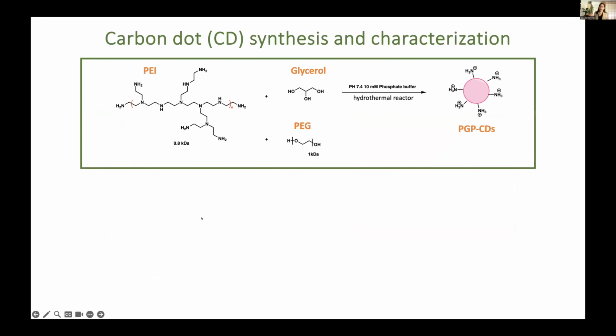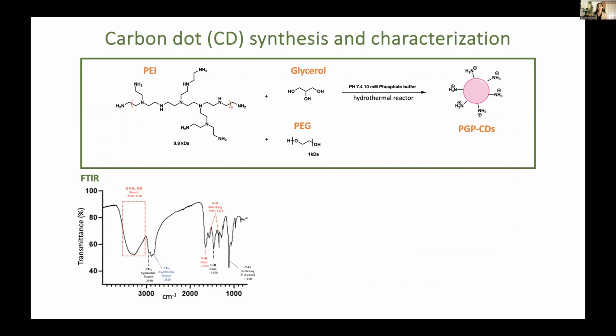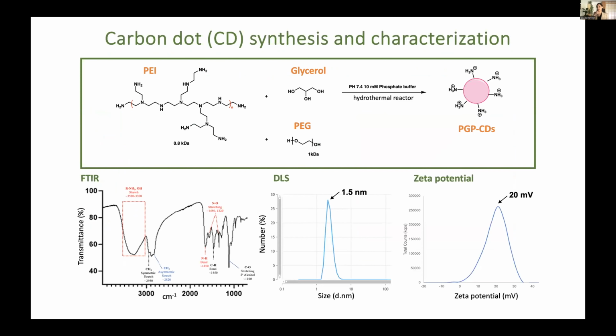So we thought that given carbon dots are very small, maybe they'll be able to enter these stem cells. So we synthesized them from a positively charged polymer, polyethylenimine, glycerol and PEG, a very easy synthesis. And then we characterized through FTIR that we actually get the correct material and the functional groups, and that these are very small, around 1.5 nanometers, spherical, with a surface charge of around 20 millivolts.